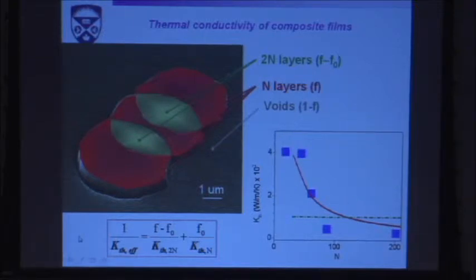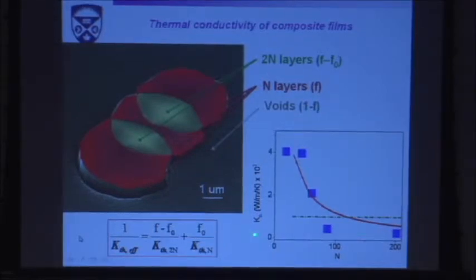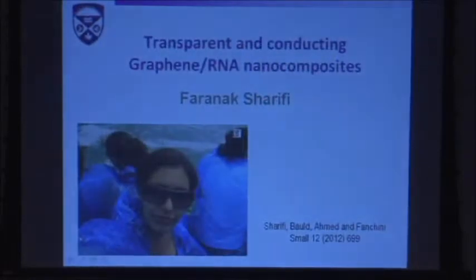Well, if you're using just the pure Klemens formula for n layers, the average number of layers, that doesn't explain a lot. The decrease is much slower. It's purely logarithmic, so very slow, almost a constant. You don't even realize that this line is a decreasing function on this scale.